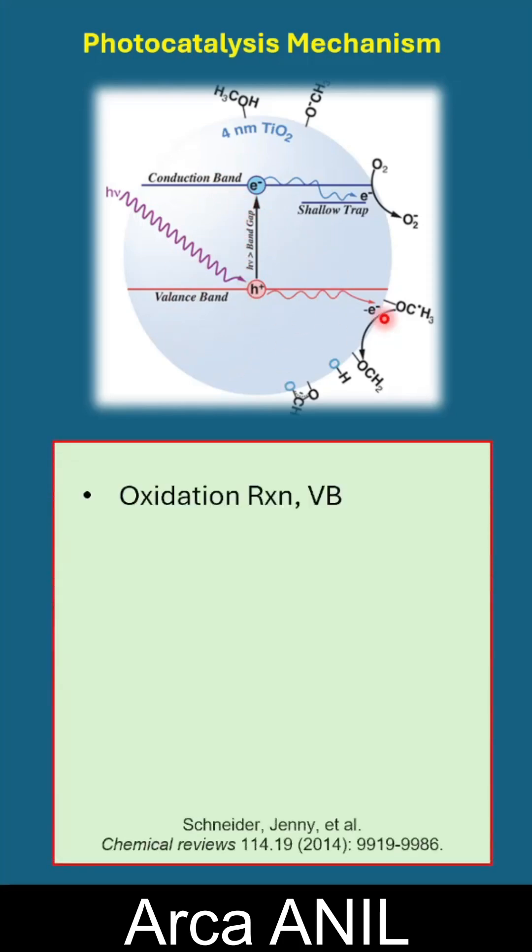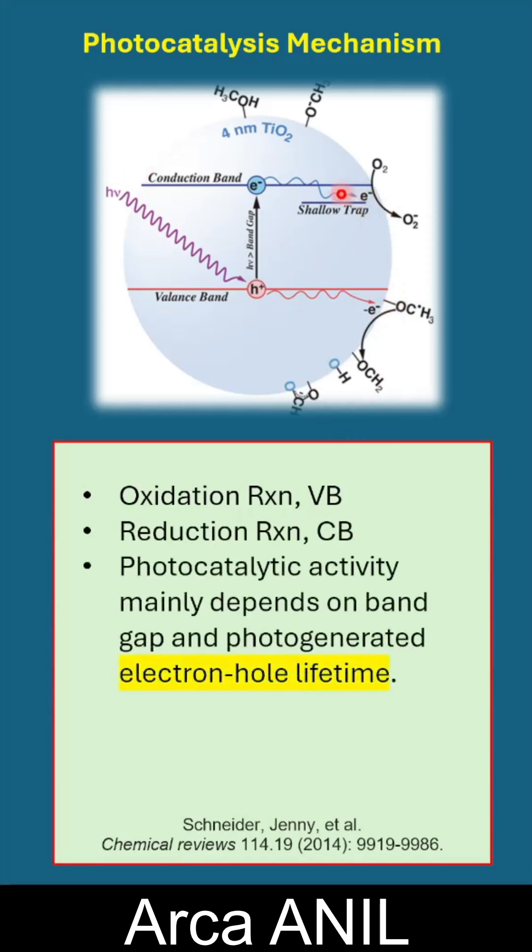Oxidation reactions happen in the valence band and reduction reactions happen in the conduction band. Photocatalytic activity mainly depends on the band gap and photogenerated electron-hole lifetime. The lifetime of the electron and hole is crucial for photocatalysis, and anatase is the best photocatalyst among the three phases.